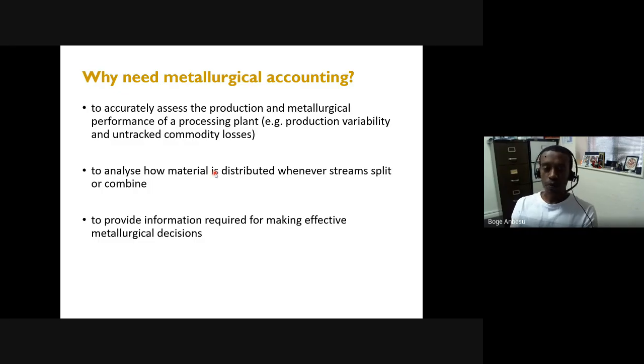So the other thing you can also do is, yes, we processed 2 million of that. This amount was copper. So you say, then we recovered 90% of it. Maybe you recovered 80% of it, and so on. Again, how do you know how much you recovered? You also know how much went to the concentrate during your mineral processing, how much copper went to the tails and lost during your processing. How do we do that? We take samples from the concentrate and the tails. We analyze that. We take the average over a year. We can also work out how much was lost to the tails, how much was recovered in the concentrate.